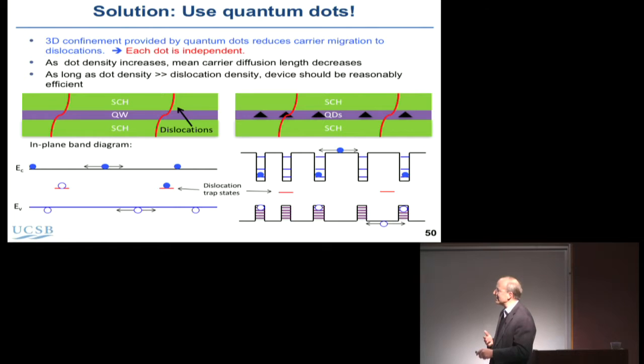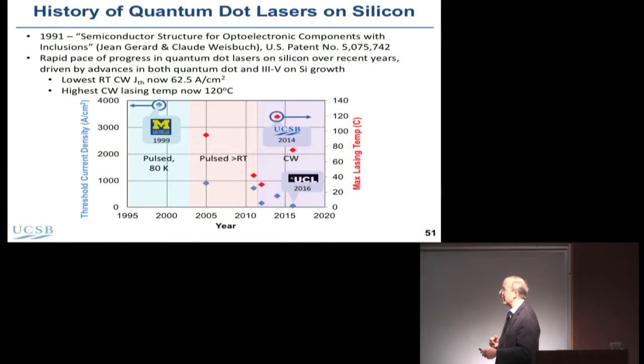This high dot density is also why the diffusion length is a lot lower, because carriers in here tend to see a dot and fall into that dot. Rather, if they're up here, they fall down into this layer and get trapped. So if this is a surface with surface recombination, then only the dots very close to that surface see it. So the diffusion length is shorter, and we see lower threshold for small devices. That's why HP is able to build 5 micron rings, and we've made devices that are actually 1 micron ring diameter. You couldn't do that otherwise. So this is sort of where that field has come.